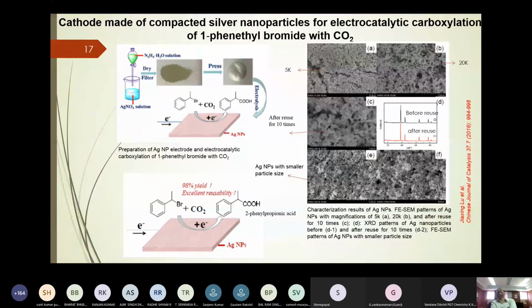There are various sizes, for example, 5K plus 20K. Okay. There they have shown that silver nanoparticles have a very small particle size. Okay. Here the XRD, X-ray diffraction, shows before use of these silver nanoparticles, and then after use of this, that reveals that there is no change in the XRD pattern of silver nanoparticles.